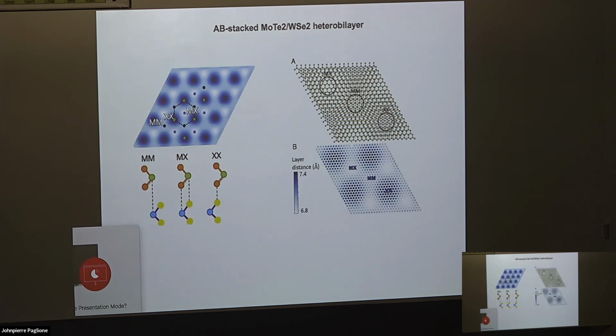When I was reading this paper, one thing that struck me is we tend to think about these layer stackings, but we don't realize how complicated it is. Not only do you have those moire bands, but if you look here, this is plotting layer distance. These layers are not just sitting flat on top of each other. The distance between the layers is actually changing. You have places where it's 6.8 angstroms, places where it's 7.4. So it's really complicated. They're just not sitting flat. That's something I hadn't fully appreciated until I saw it in this paper.